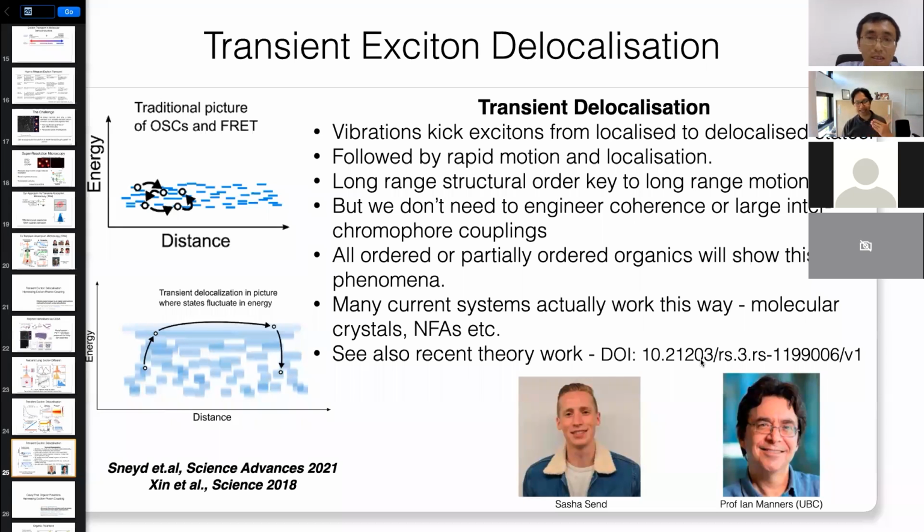So on the energy gap in these systems, if you imagine what a CC stretch can do, right? If the CC stretch is 180 meV, that means it can move that exciton, say 100 meV one way or the other. So 100 meV is quite a lot. And so these delocalized states are not like 500 meV above. They're maybe tens of meV, 100 meV above. And so it appears that that is already enough to do this.